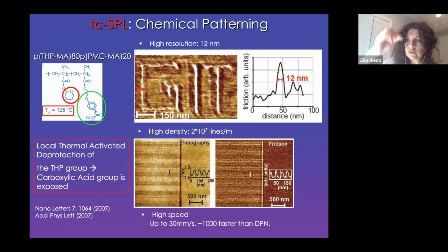So what you can do, you can heat locally the polymer, and you can deprotect the polymer from these groups, and you can expose carboxylic acid groups. So this is what you have here. The white area here is where the protective group has been removed, and it is where you have carboxylic acid groups. This is a friction image. Why friction? Because friction tells you that some chemistry is happening here.